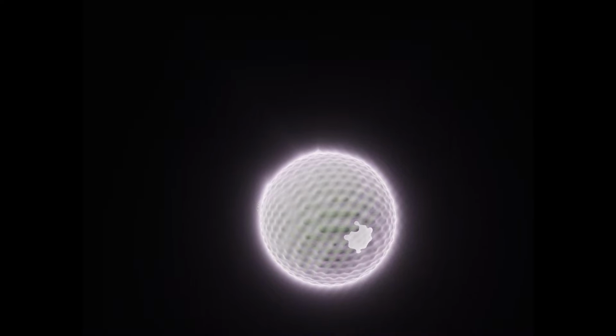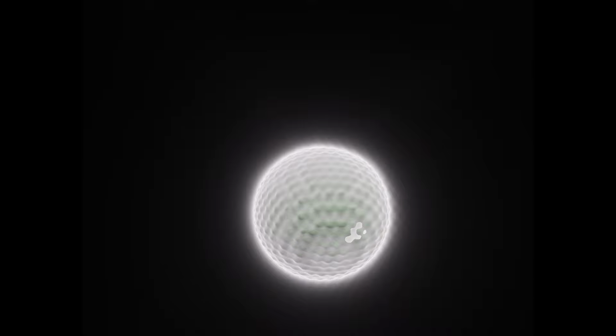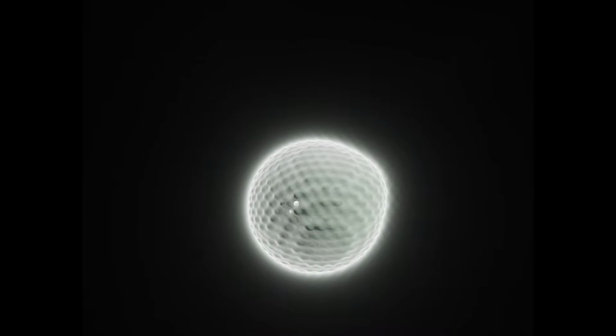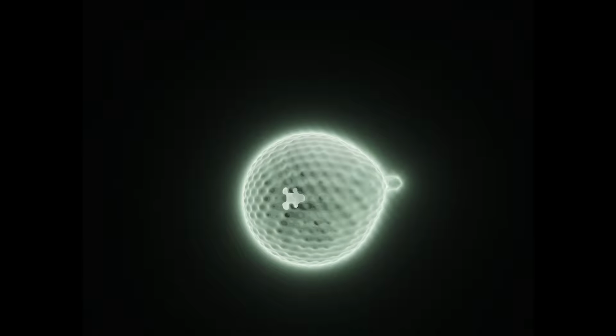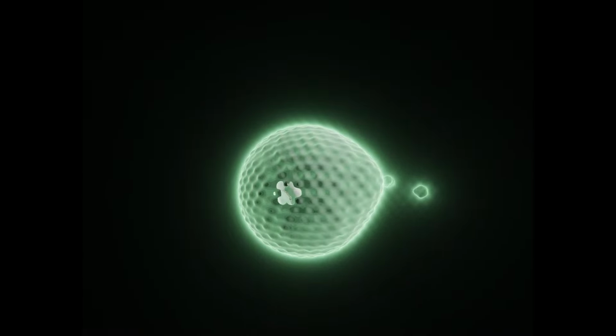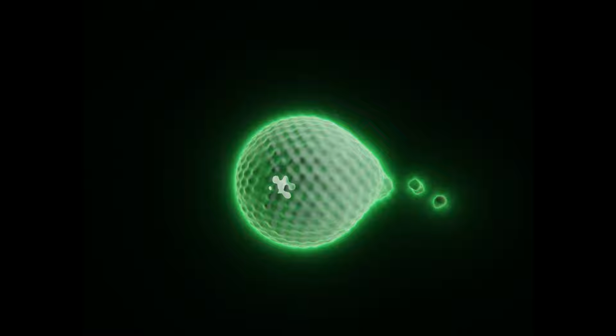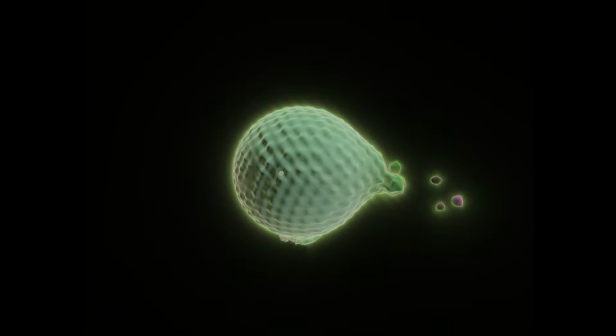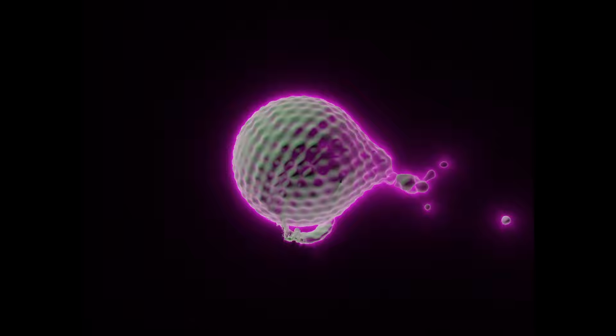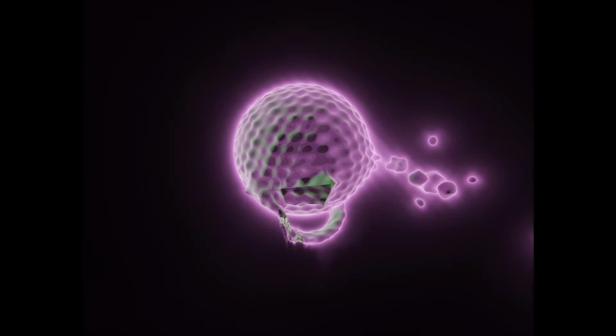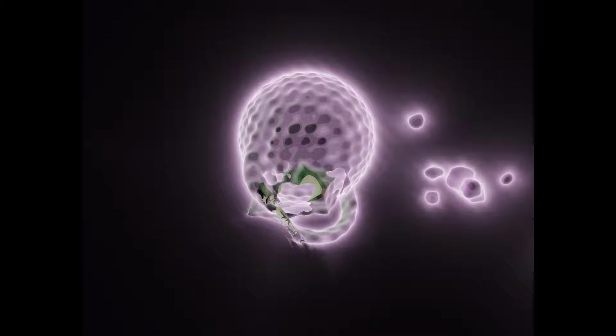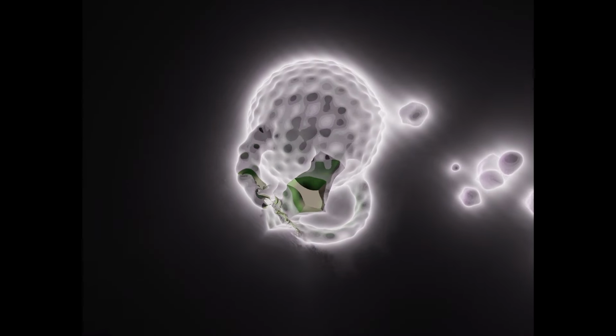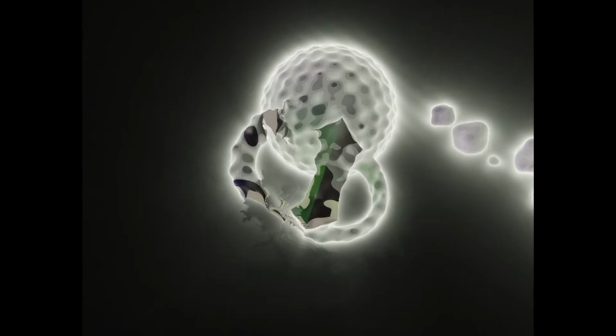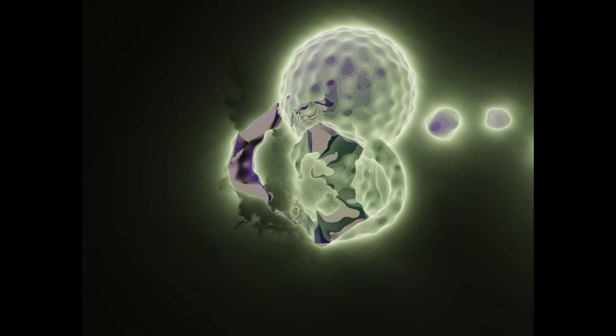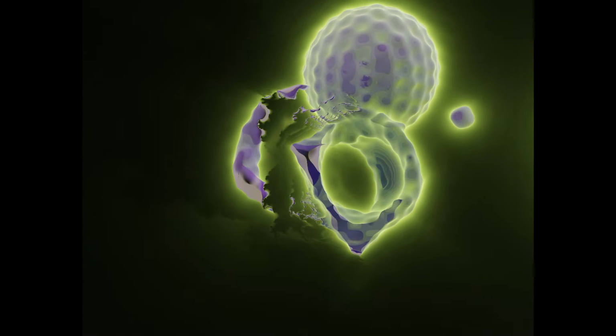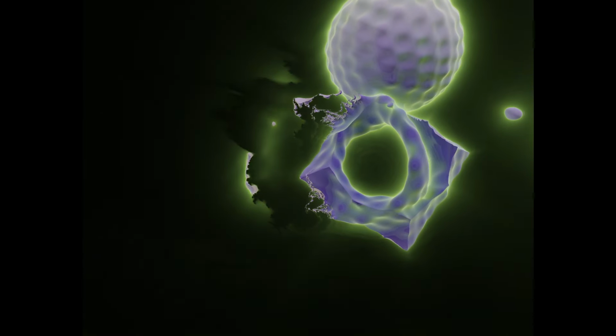So how do you dope 2D materials? We need new, non-destructive strategies. Things like surface charge transfer doping, where molecules sitting on the surface donate or accept electrons, or in situ doping, where you introduce the dopant atoms during the CVD growth process itself. But getting that right must be hard, like getting enough dopants in, evenly spread. Exactly. Achieving the high concentrations needed for real devices with good uniformity across the wafer and making sure it's stable over time. That's still a formidable challenge for industrial scale.